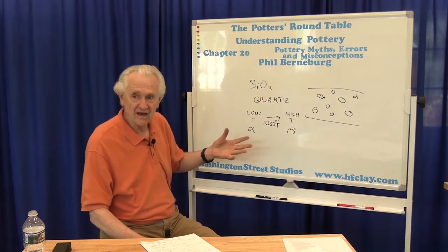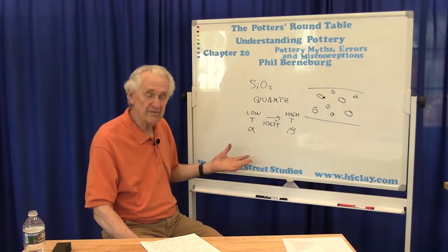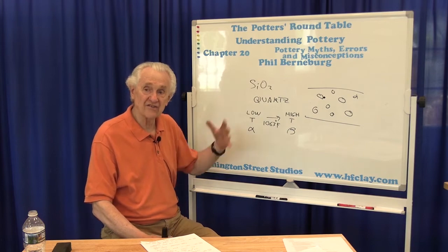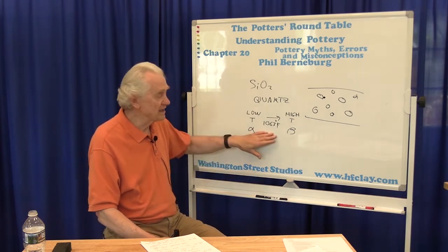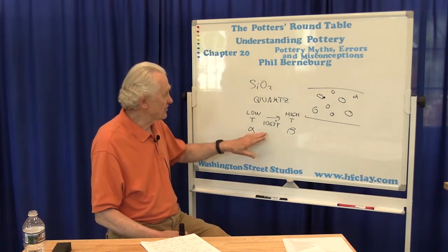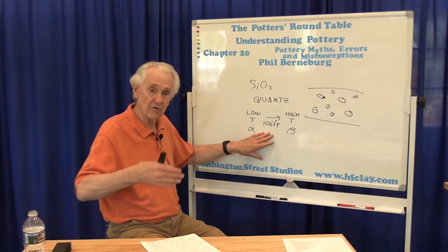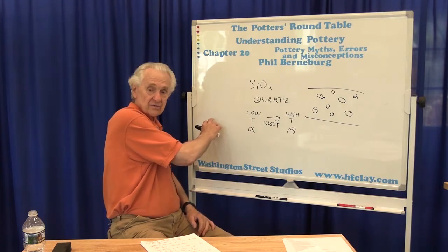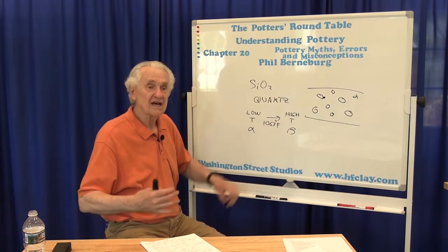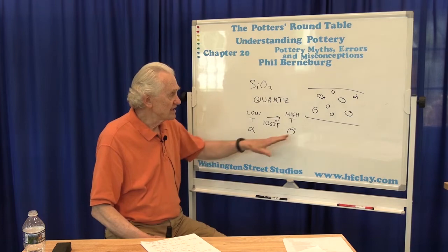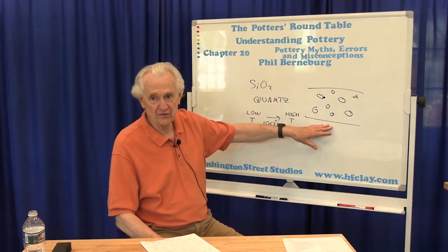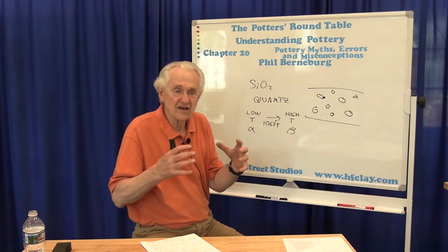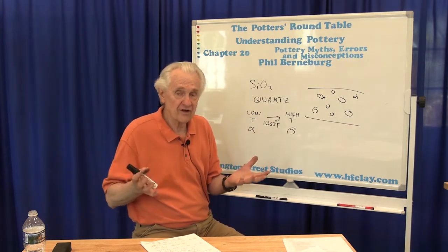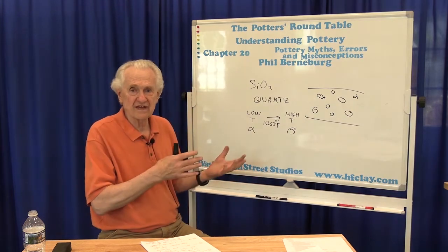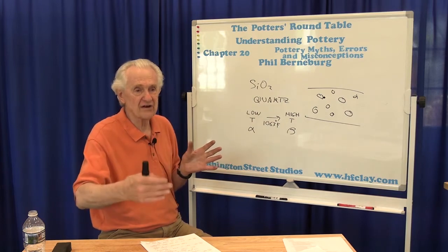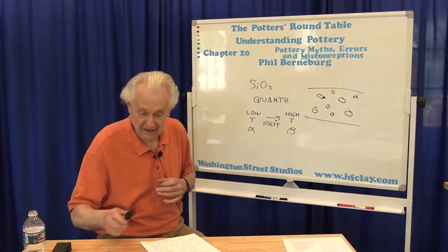Now, again, I'm sort of wondering, where did this belief come from? What might be, if you were refiring pots in the same firing that had already been glaze fired and you heated them up too quickly, then it's possible that both the quartz and now there might be some cristobalite in the pot. So I might have quartz and cristobalite. And when the cristobalite grain goes from low to high and the quartz goes from low to high, they both expand. Yes, it's possible that they could cause cracking of the pot, but I don't believe, frankly, that this is a serious issue with bisqueware, because the bisqueware is so porous, it isn't tightly packed. There's room for all those little quartz grains to expand without destroying the whole pot. So I'm guessing that maybe that's where this belief came from, the fact that in the same firing, people might be refiring pots. And yes, in that case, it's very possible that they could crack.